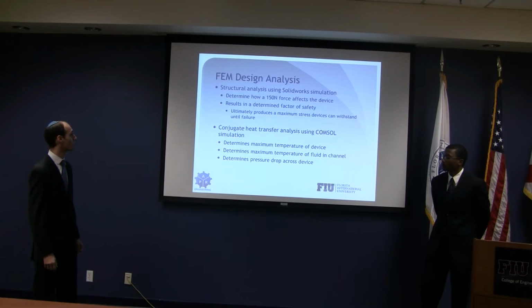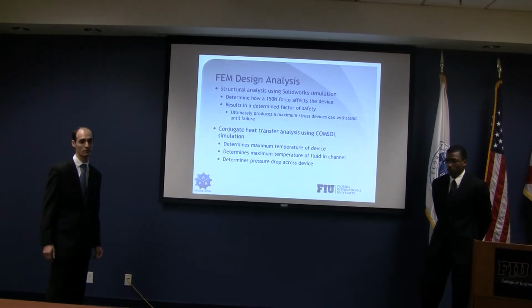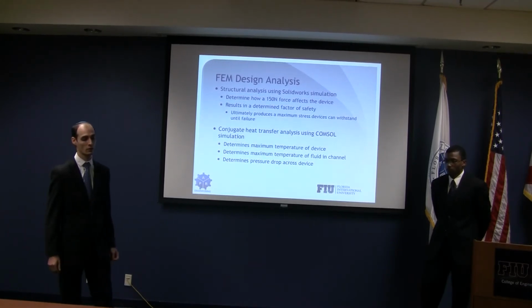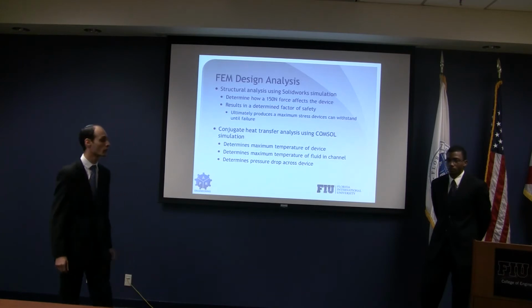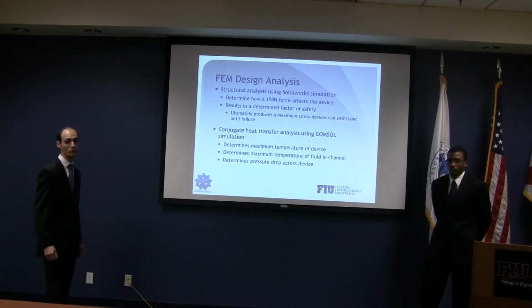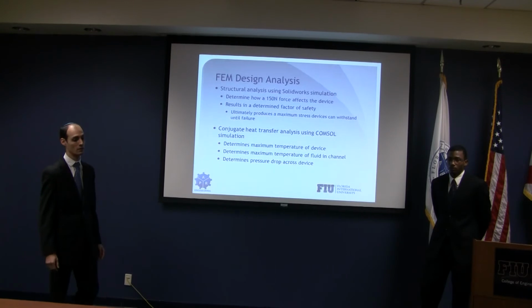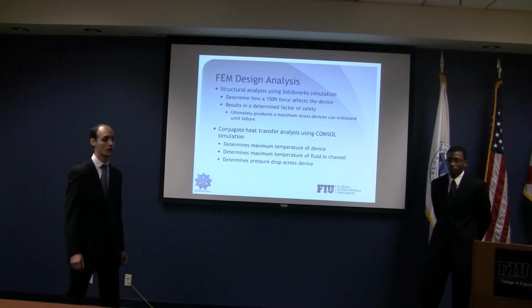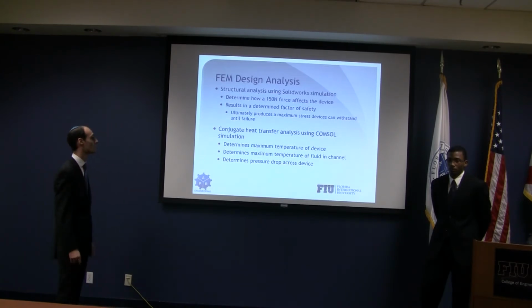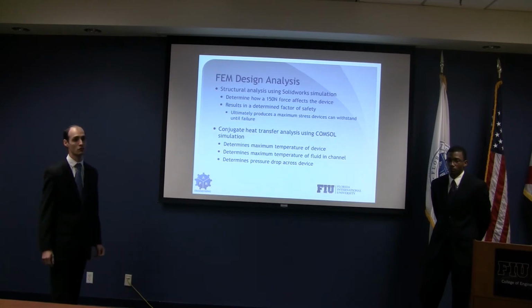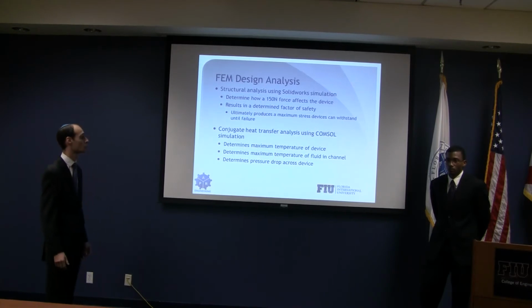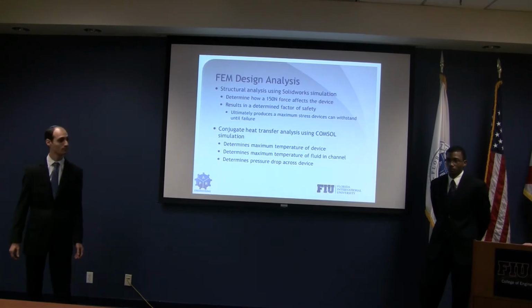We proceeded with an FEM design analysis. We used a 150 Newton force, and we determined the safety factor, what the maximal stress would be that a device can withstand before failure. We then did a conjugate heat transfer analysis using COMSOL, and that would determine the maximum temperature of the device, and it would determine the maximum temperature of the working fluid, which is water. We needed to avoid boiling, and the pressure drop across the device.